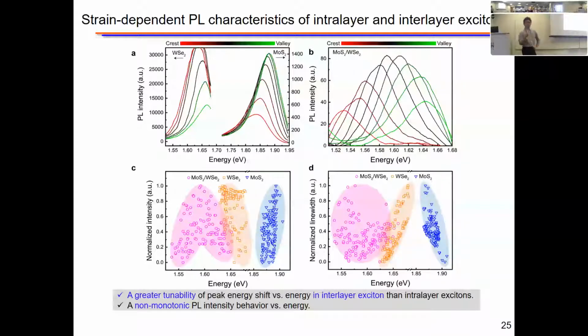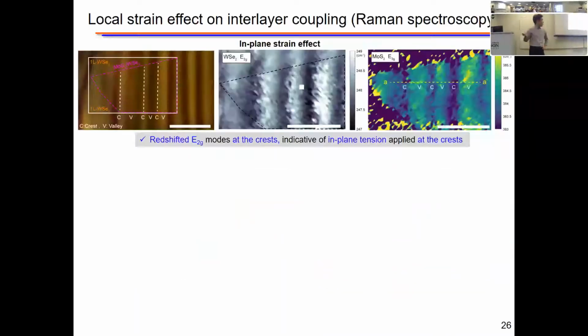We observe a really remarkable qualitative difference compared to the intralayer exciton. We observe greater tunability and also non-monotonic behavior of PL intensity, where we observe the maximum intensity at the intermediate state as opposed to either crest or valley in the case of intralayer exciton. So we're curious about why this is happening.